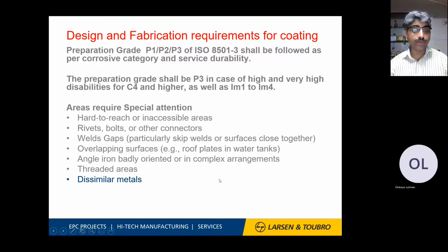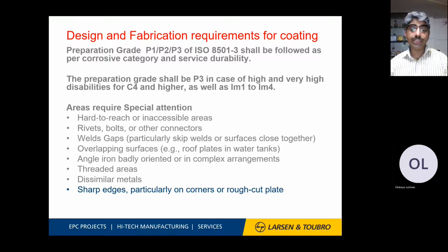There is one hour lecture we can give only on dissimilar metals, as this is the only area where you want to protect the more noble metal by painting its surface. This is just one takeaway for this lecture. Other is sharp edges, particularly on corners and rough cut plates. We have a subsequent slide where I will address this point again: sharp edges and corners always have lesser DFT, that is dry film thickness, over the surface. Because of that, it is going to be a problem for longer life of that component, and corrosion starts from the edges. Again, construction errors. Normally, construction errors are always to be addressed when we design fabrications for any coating systems.